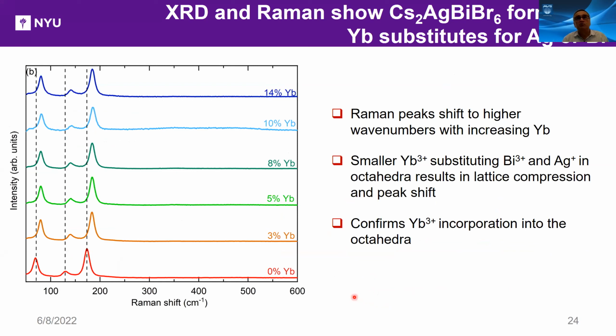Raman spectra is what shows the substitution of ytterbium for silver or bismuth. And you see here the metal bromide peak shifts to higher wave numbers with increasing ytterbium concentration. Ytterbium is smaller than both bismuth and silver, so in the octahedra it results in lattice compression, and that lattice compression is expected to give a Raman shift. So this data is actually pretty clear, the shift, and confirms ytterbium incorporation into the octahedra. We can't tell whether it's going into the silver or the bismuth yet, but we have some data to suggest that we might be able to, but we haven't yet got to the bottom of that.